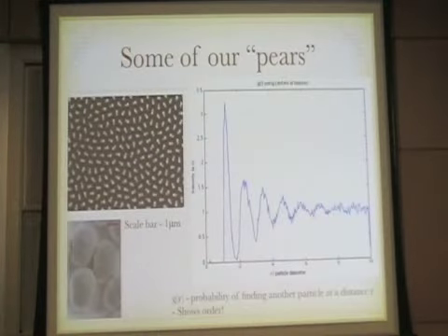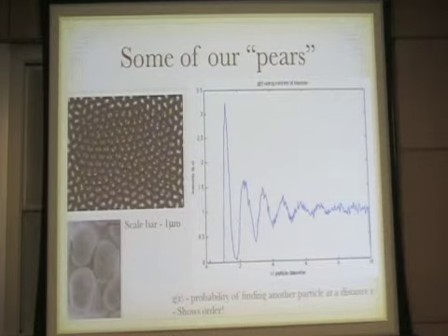Let's take a look at this picture. Here's the SEM of the particles that we have. This is a g(r) plot, the pair correlation function. The peaks show that there is certain long-range order in this system, so we are talking about a crystal. It's not just any random picture. In this plot, we track each particle, and if it's surrounded by 6 nearest neighbors, we color it black. So there is some sort of hexagonal, or 6-fold, symmetry here.